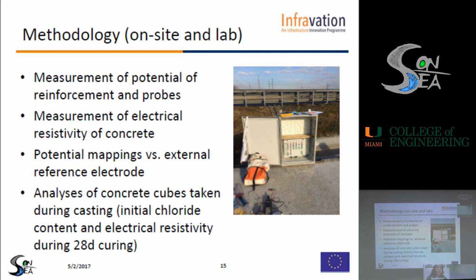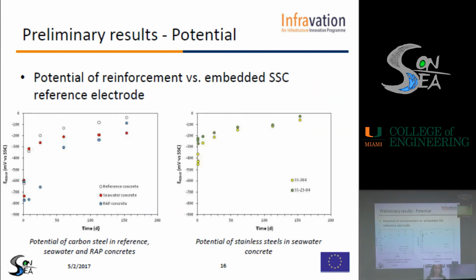Then after 5 months, which is basically last week, we also made a potential mapping. So we measured the potential of all the grid in each segment with respect to an external reference electrode. And finally, we also performed some analysis on some of the concrete cubes that were taken during casting. In particular, chloride content. However, I will not discuss this today because we had some strange results that we are still going to clarify. And also we measured the electrical resistivity during the first 28 days of wet curing of the cubes.